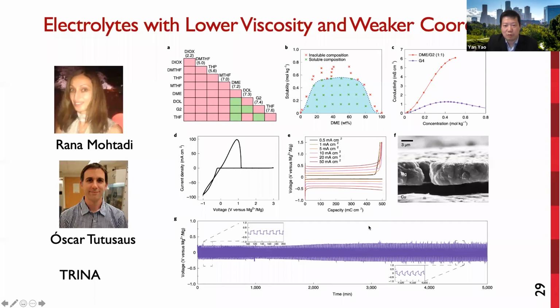We can also apply similar conditions for symmetric cells over 5,000 minutes. The smooth voltage profile indicates effective mass transport in the electrolyte. So these results consolidate magnesium metal as a safe anode even under demanding conditions.